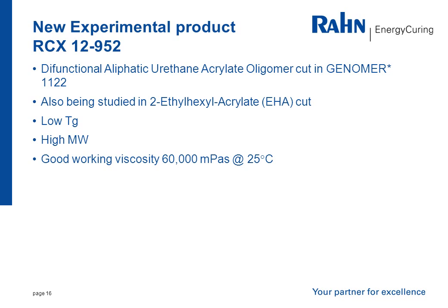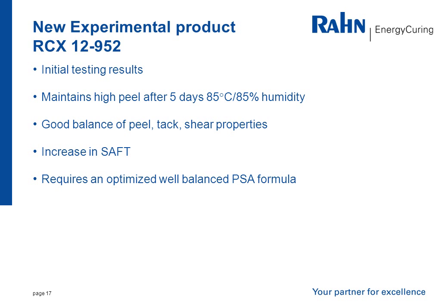RCX-12-952 is a difunctional urethane oligomer cut in Genomer 1122. It is also being studied in a 2-Ethylhexyl-Acrylate (EHA) cut version. It offers low Tg, high molecular weight, and a good working viscosity of 60,000 millipascals at 25 C. Our initial test results indicate maintenance of high peel after 5 days at 85 C and 85% humidity.